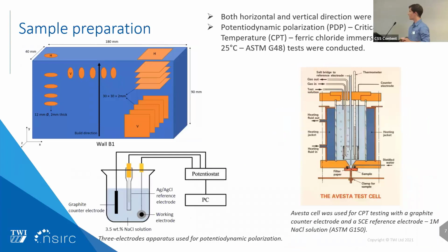Samples were extracted from the two walls. We had disk samples that we used to do potentiodynamic polarization scans, using a 3-electrode cell described here. We used a graphite counter electrode and a silver chloride reference electrode, done in 3.5 weight% sodium chloride solution, all at room temperature and in open air.